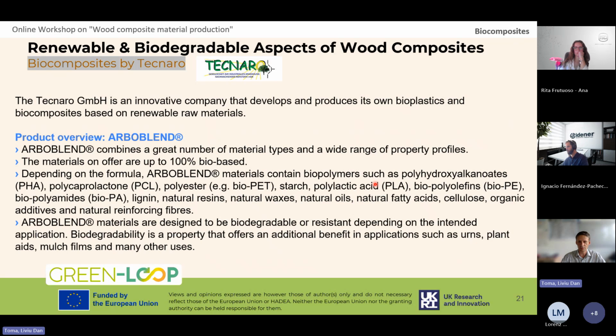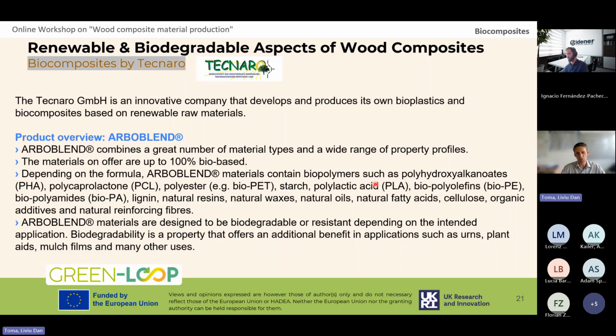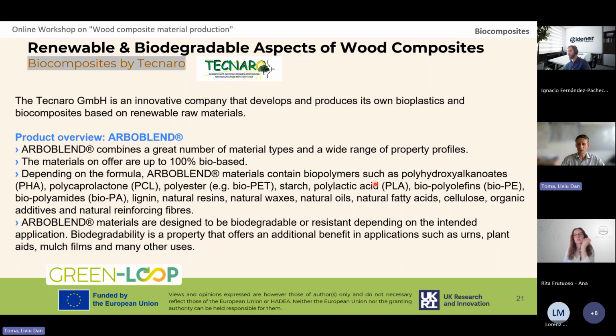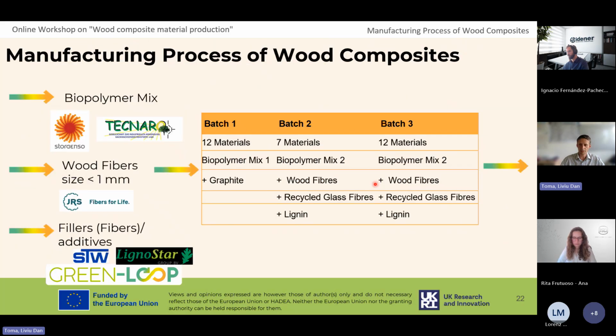One of these alternatives we found in the form of ARBOBLEND® products, which were supplied by Tecnaro. This is a material which is up to 100% bio-based and contains biopolymers like PHA, PCL, PET, PLA, and so on, and also has already included in the formulation lignin, natural resins, and so on. And with this, we continued our work.